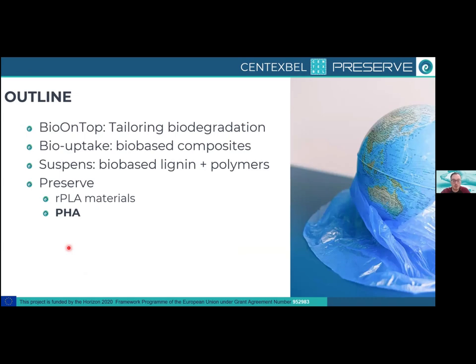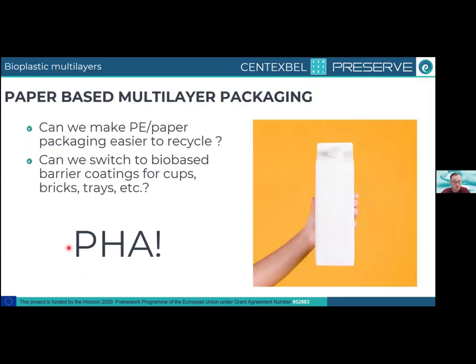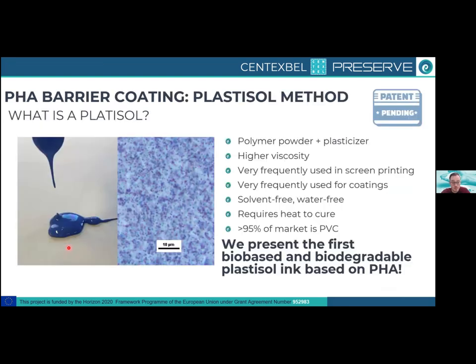Then lastly I will go over to the PHA that we have used. So in PHA, how is this used in Preserve? There are actually two main questions that we are addressing using this PHA in multi-layer packaging. So first of all, can we make a polyethylene paper packaging easier to recycle? And then secondly, can we switch to bio-based barrier coatings? So using fully bio-based materials, can you actually reach these high requirements for barrier coatings that we need in the demonstrators we have for cups, bricks, trays, etc. So PHA can be a solution to this.